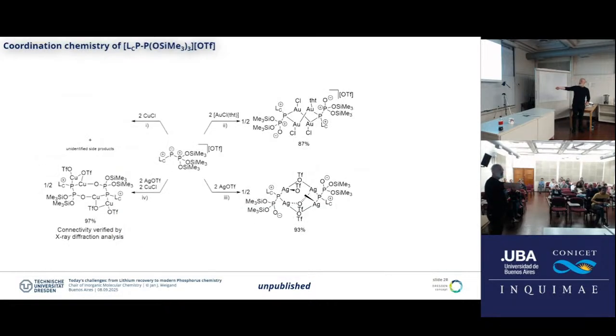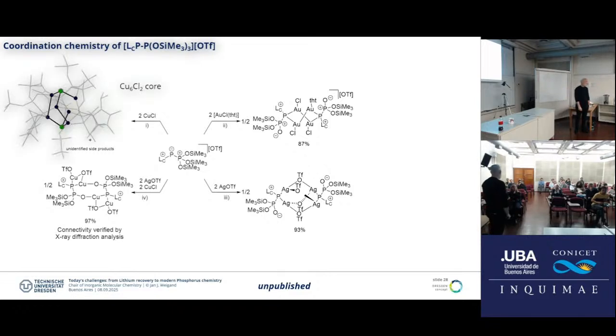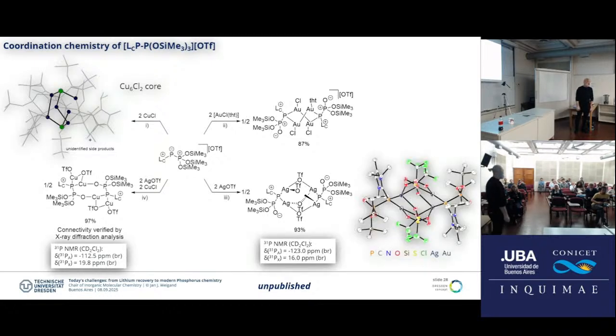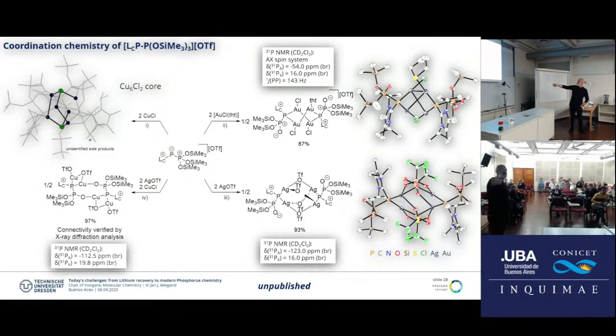So we've done this with copper chloride. Again, you can use a halogenide to cleave the trimethylsilyl group, building the trimethylsilyl chloride bond. And you make a coordination complex. You make a copper 6 core. In the case of copper and silver, you make these tetranuclear complexes. But be aware that we still have these PP bonds. We have not yet cleaved the PP bond because we just stopped at the first desilylation step. Gold also makes more or less the same, but you see a very funny thing when you see already metal-metal bonds. So this is already a gold 4.